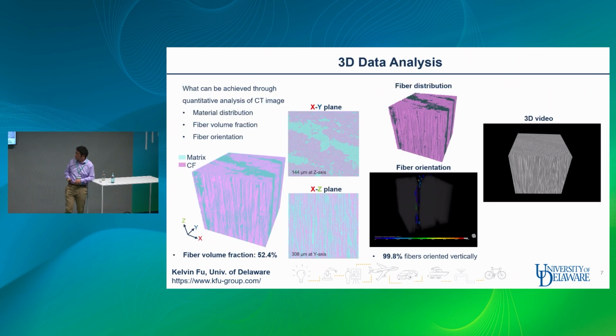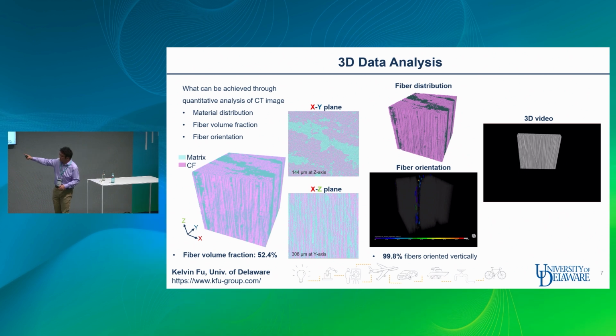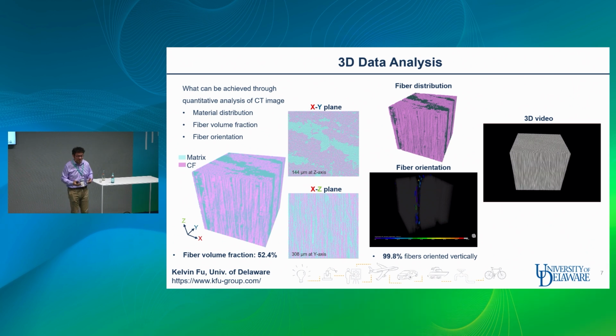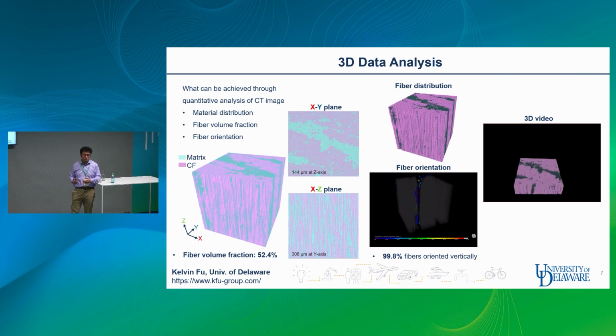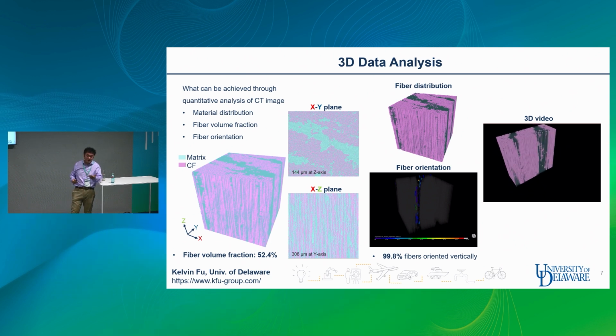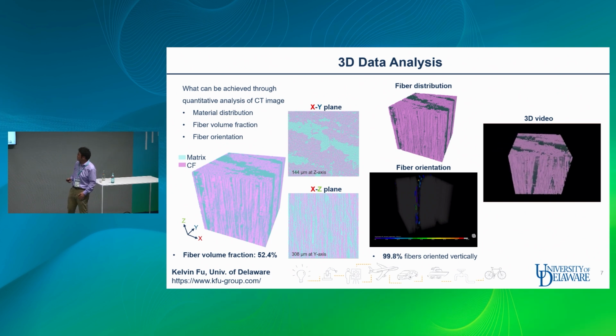It's a pretty good structure. And also we are using the nano CT to study the fiber volume fraction. If you look at there, the fiber volume fraction based on the 3D data we obtained by the AI is 52%. It's similar to the experimental results from the samples. And also 99% of fibers are aligned, super aligned. So that confirms this technology can print highly aligned continuous carbon fiber.